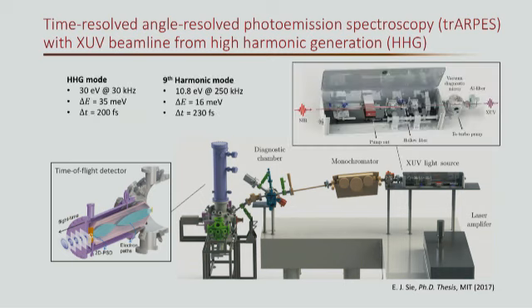And then we generate the XUV light by using inert gas in a hollow fiber. There are two operation modes for our trARPES setup. In the high harmonic mode, we send in a very intense ultra-short pulse of near-infrared light. And then by a high harmonic generation process, we can produce up to 30 eV at a 30 kilohertz repetition rate of lasers.